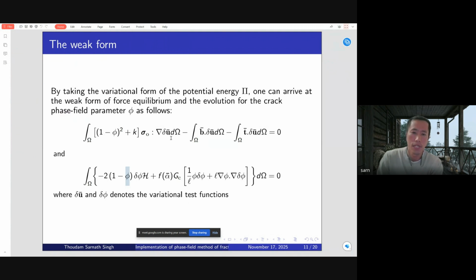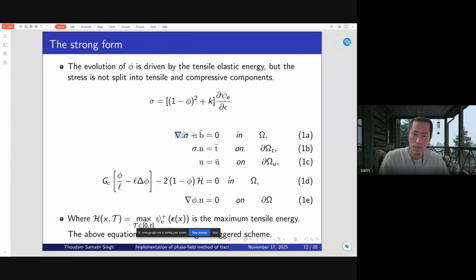So this is the phase field phi, and this whole equation is the phase field evolution equation. From this weak form, if we expand it and apply the divergence theorem, we can arrive at the strong form. This is the force equilibrium equation, and this is the Allen-Cahn or the phase field evolution equation. And this evolution equation is driven by this function H. This H is nothing but the maximum local tensile energy. We can think of it like this: when we load the material at the material point, this is the maximum local tensile energy in the material.